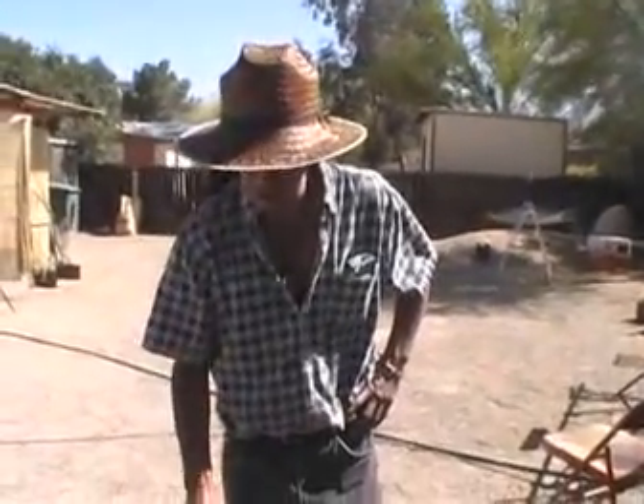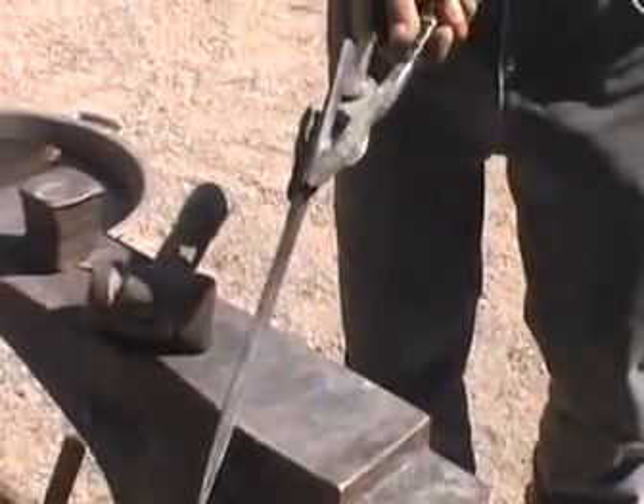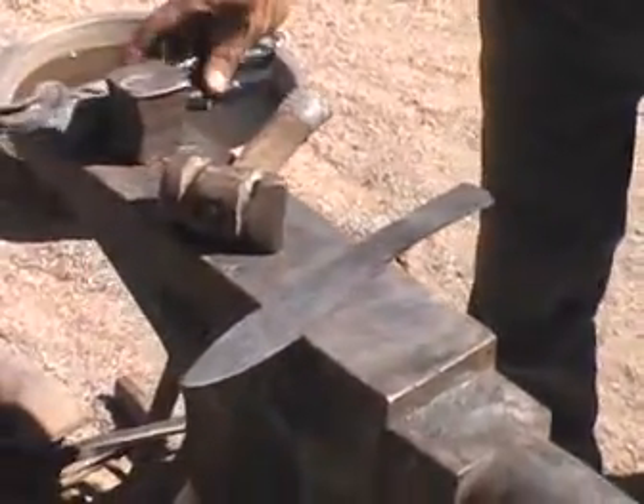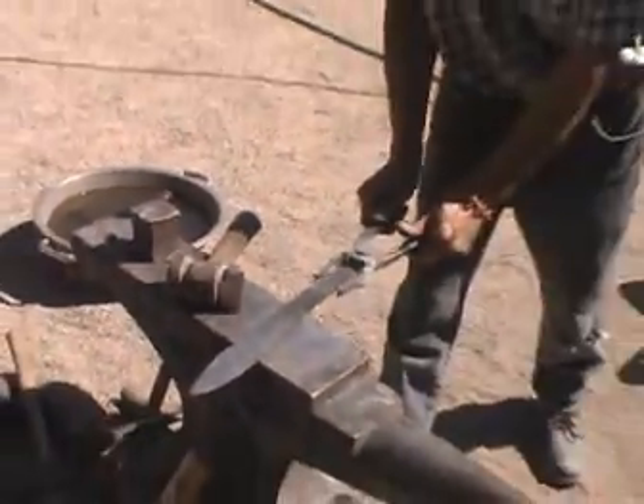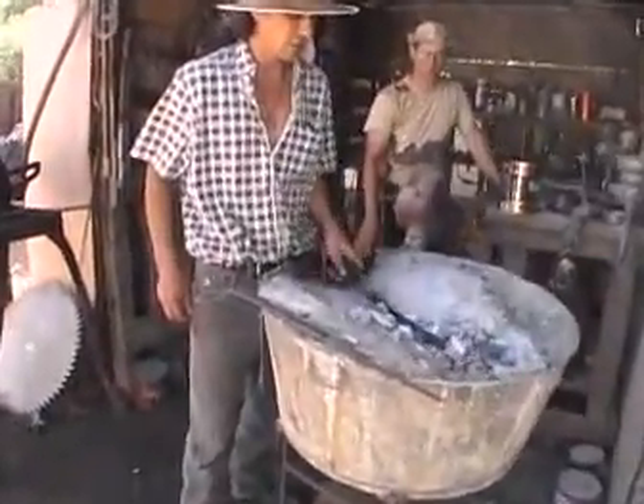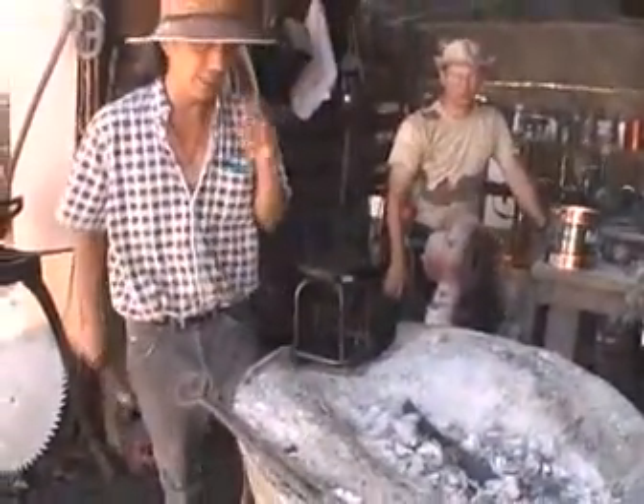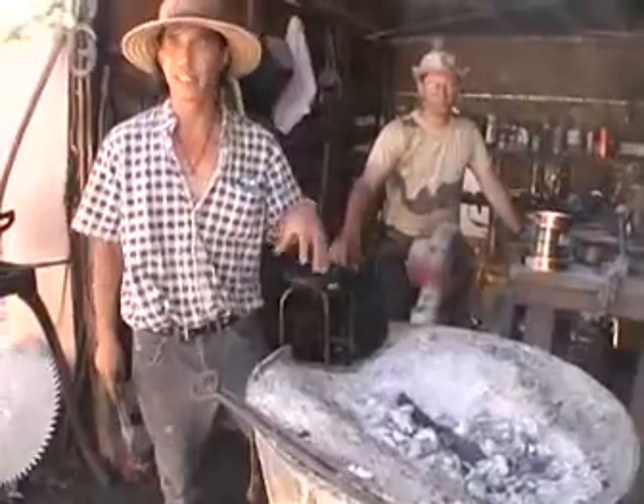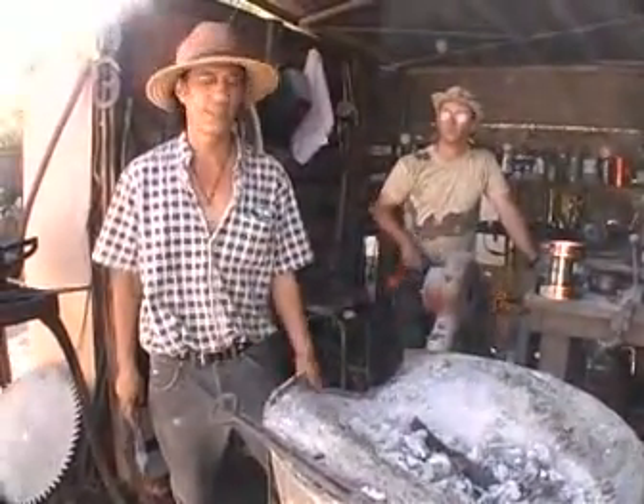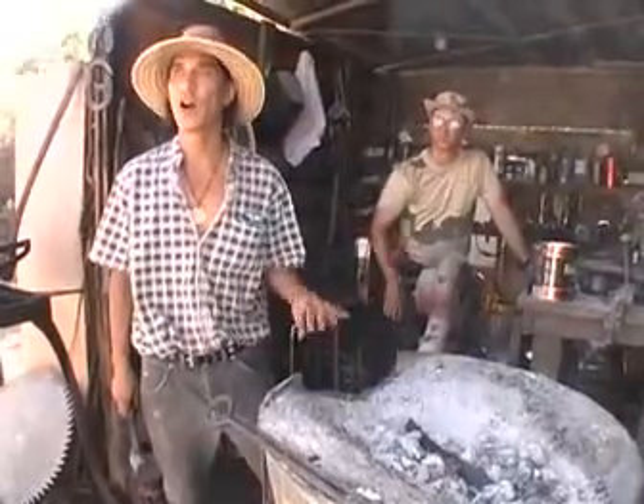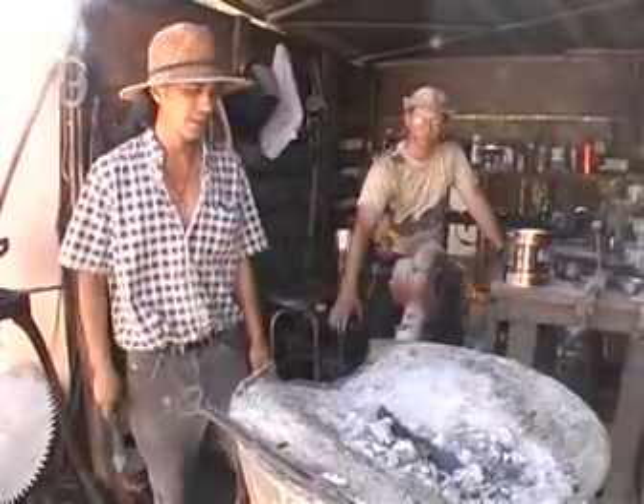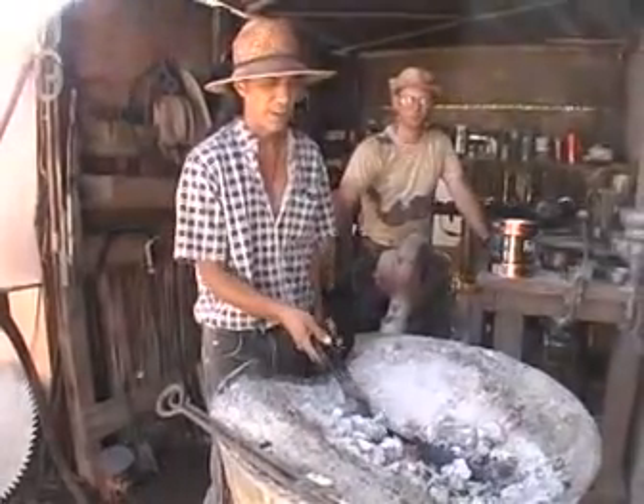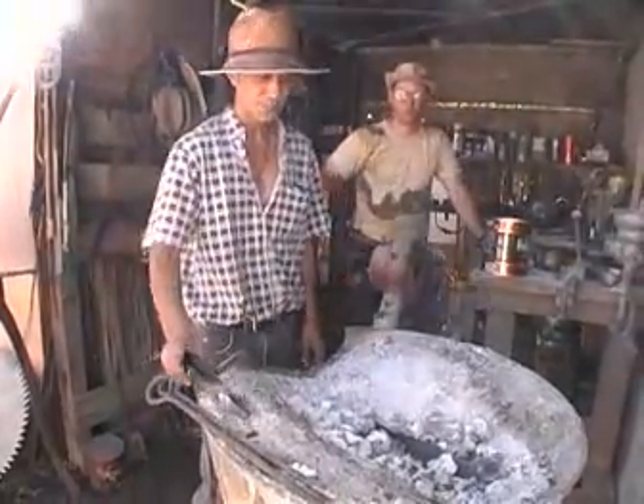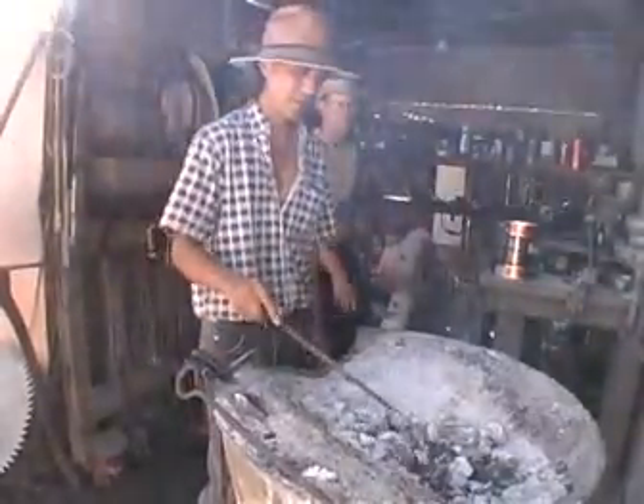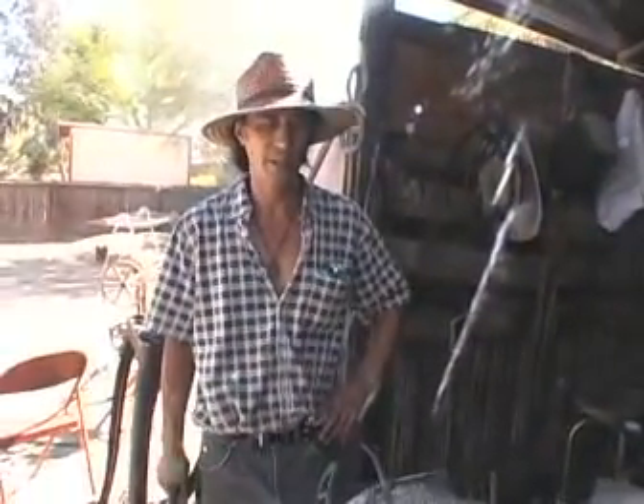I guess we'll call this good enough for now, and I'm going to do a little bit of stock reduction on it, and then we'll go to the hardening. So before that though, I think I'll normalize it one time here in the fire. All the normalizing is just to heat it up to the critical temperature and let it air cool. What that does is stress relieves it, and it'll make it easier to file and do the stock reduction. So it'll take any residual hardness or stresses out of the metal. It could warp too while I do this part, and if it warps a little bit, then I'll straighten it out, and then we'll get on with the rest of it. Stock reduction just means removing material from the blade.